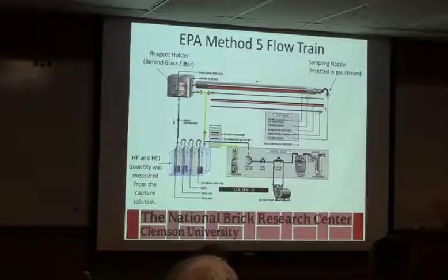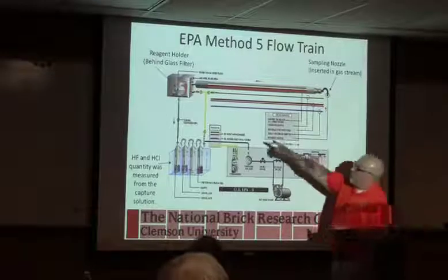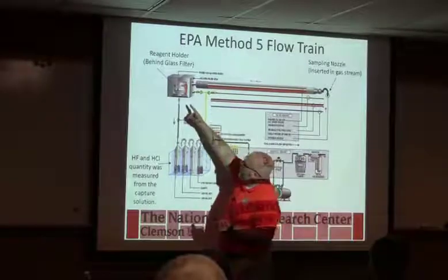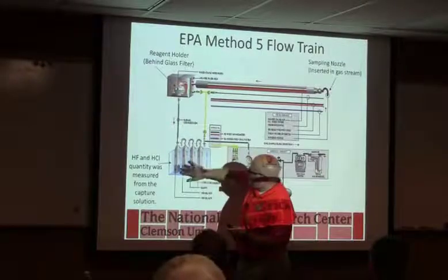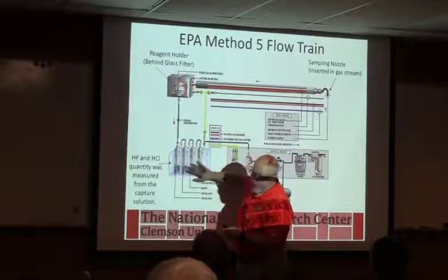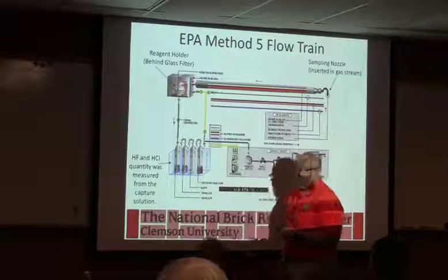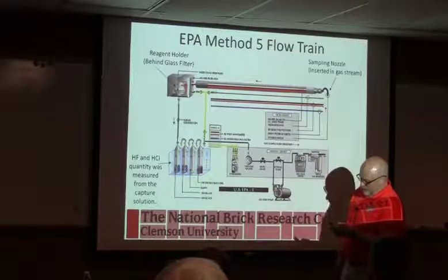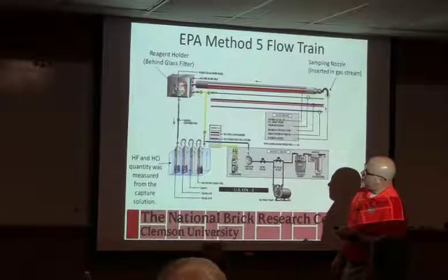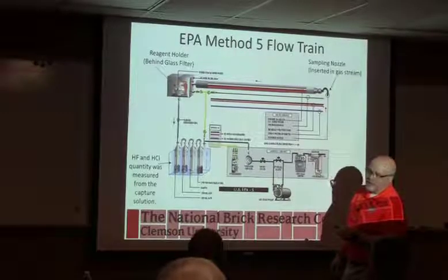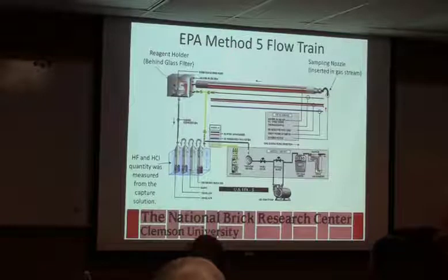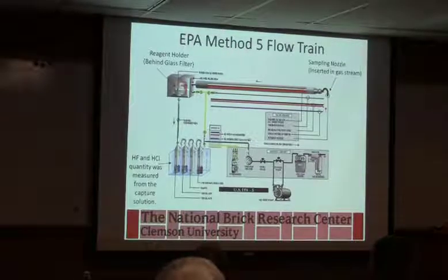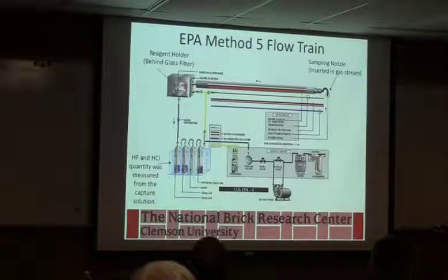But you collect the sample for a period of time. You take that filter pad and you figure out how much particulate matter you had, and then if you're doing fluorine and chlorine, you analyze those liquids and you figure out how much you collected. I've been doing a bunch of stuff lately where I take those filter pads and I've been looking for trace metals. So I go to the electron microscope lab and I see a lot of that sodium or that ammonium sulfate we talked about gunking these things up.